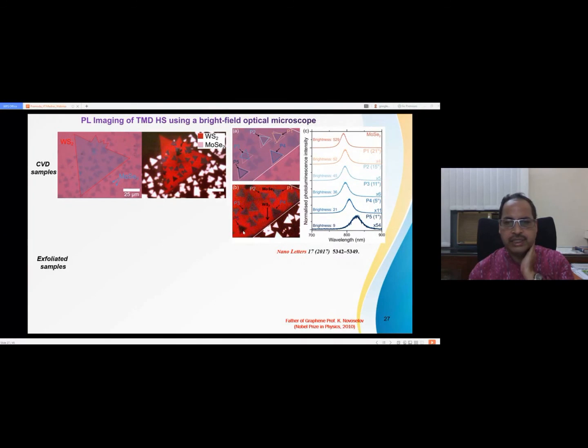When it is close to the 60 degree and 0 degree configuration, here you can see there is a large quenching. On the right hand side, you can see this is MoSe2, and this is the heterostructure at different points P1 to P5. So P5 is close to your 0 degree configuration, so there is a large quenching. It is multiplied by a factor of 54. Okay, large quenching, and the band gap also decreases. This is plotted on the wavelength scale. Similarly, in the other structure, it is low, but at a higher angle you can see the intensity is at an intermediate stage. So, using this simple technique, we have demonstrated the coupling strength between the two different layers.